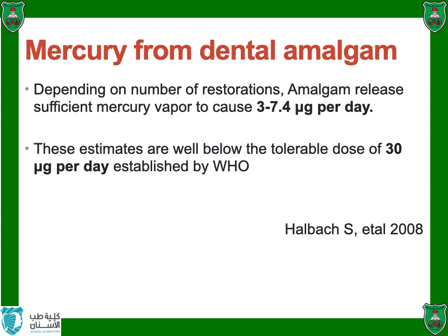Now is that a problem, the mercury that comes from dental amalgam? Depending on the number of restorations, amalgam releases sufficient mercury vapor to cause 3-7.4 microgram per day, and the estimated tolerable dose is 30 microgram per day as established by WHO. So actually the amount that enters the body from dental amalgam is very minimal compared with the tolerable daily dose of mercury.